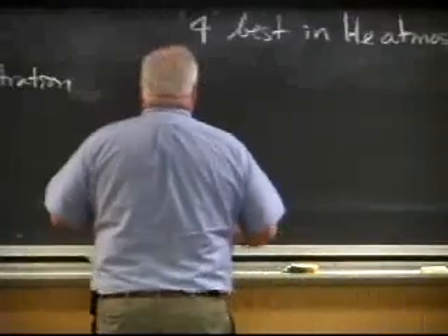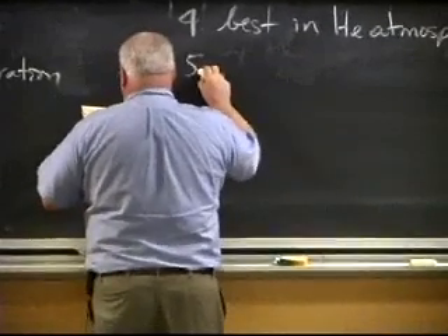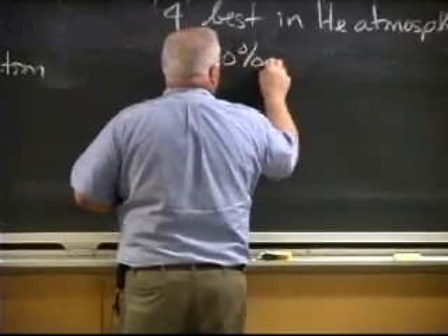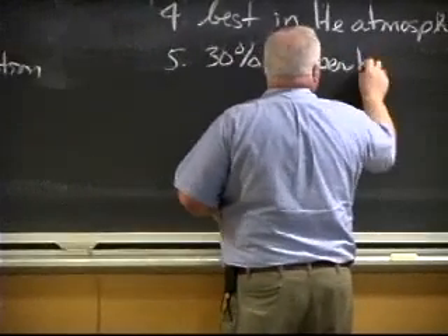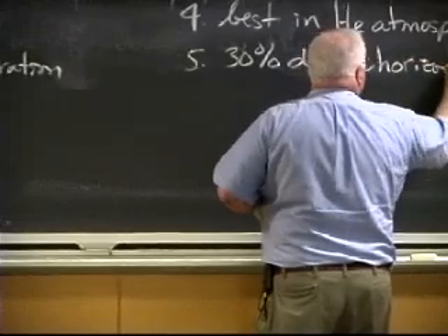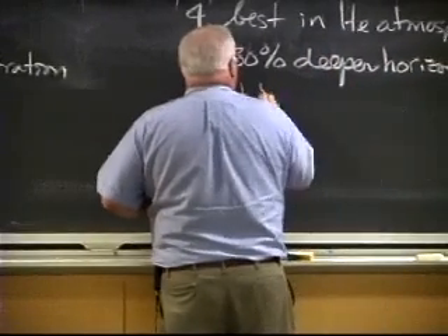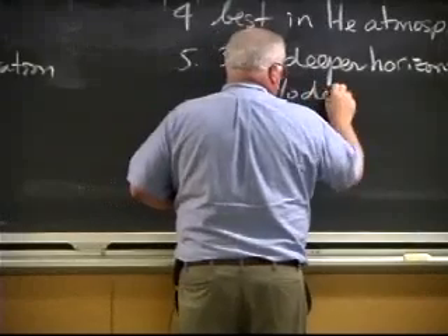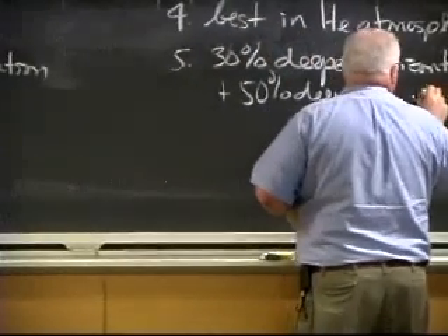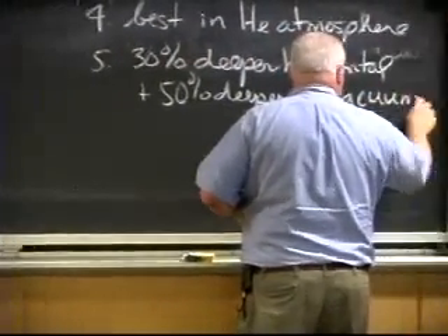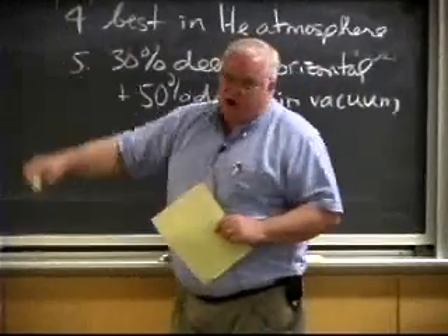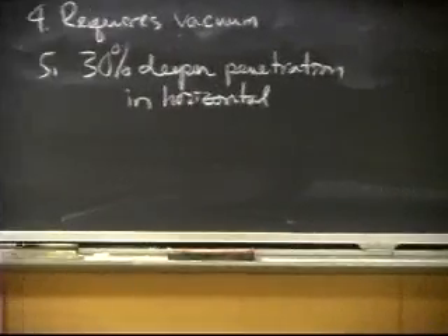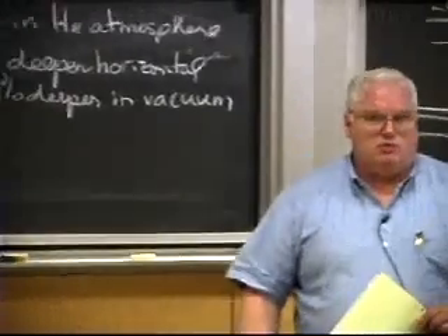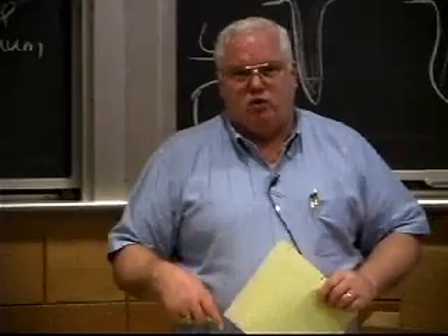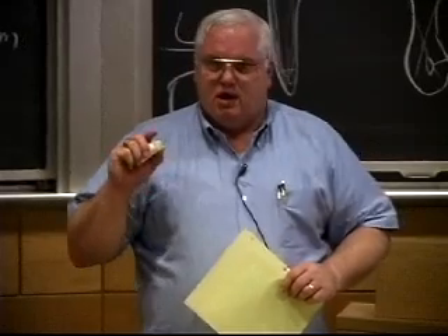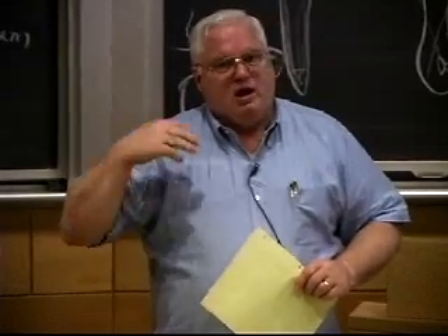Now, it turns out for lasers, you also get the same 30% deeper for horizontal, but I also get 50% deeper in a vacuum. You can weld with the laser in a vacuum, you just have to pay for the vacuum. You have to have a vacuum for the electron beam in general. You don't have to have it for the laser, which is a significant advantage. However, if you do try to laser weld in a vacuum, you will get about twice the penetration depth for the exact same beam parameters.